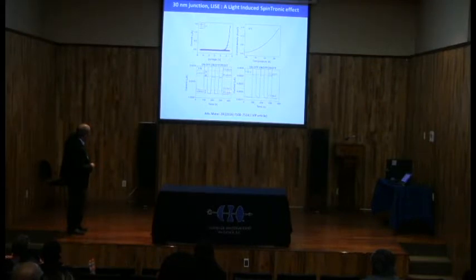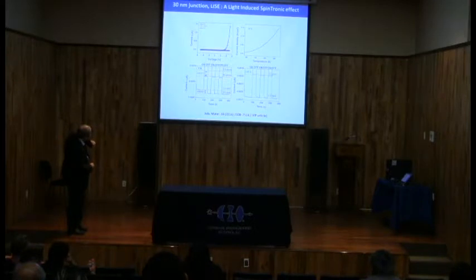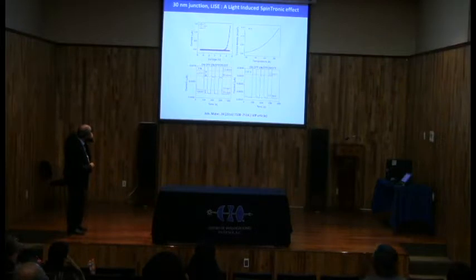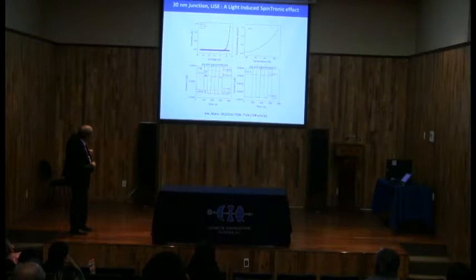if you are in dark, at low temperatures here, okay, low spin form, if you irradiate your systems, you have photocurrents like that in the low spin state, okay? And then if you continue irradiating the system, you have switching from low spin to high spin by light. That means that here you have the high spin form in the irradiated state. That means that you can compare the photocurrent between the low spin and the high spin.